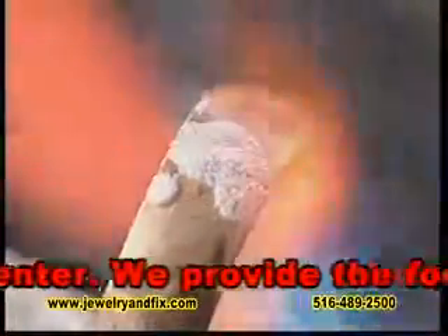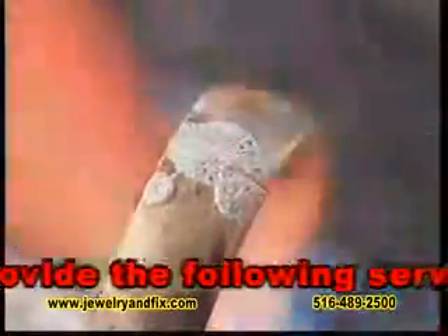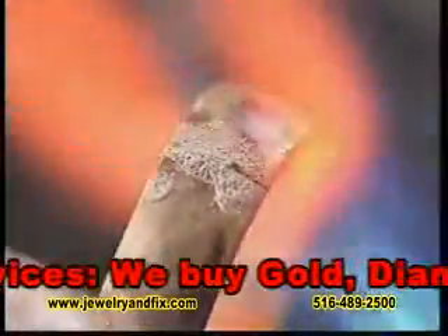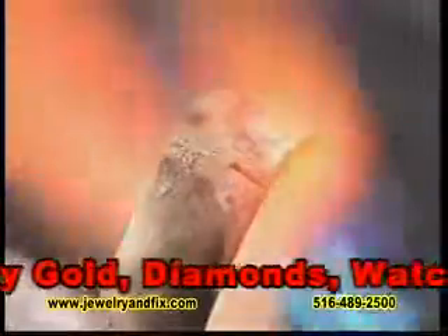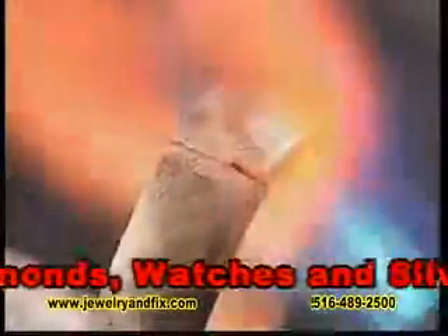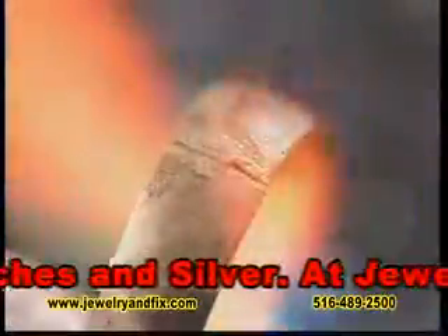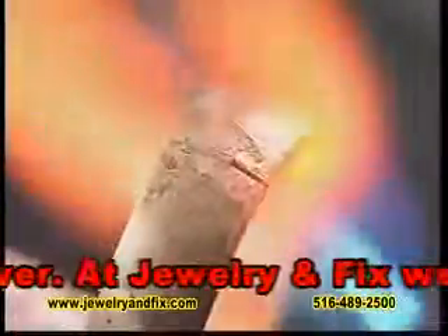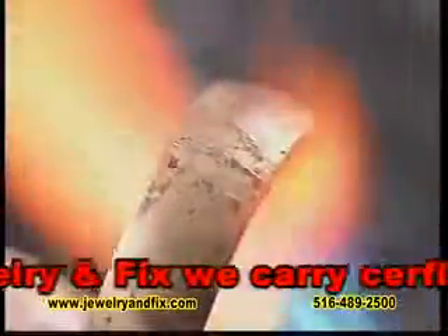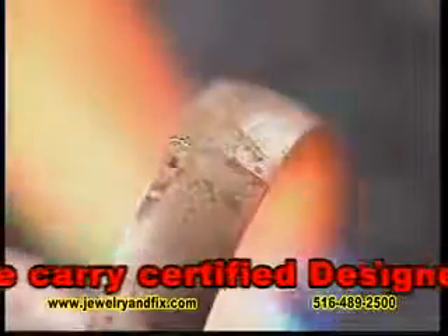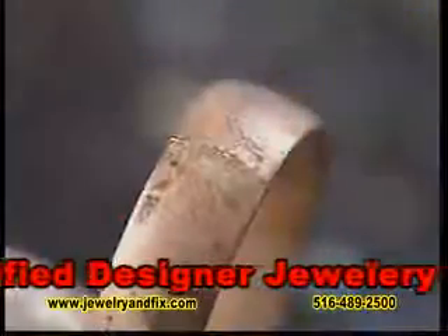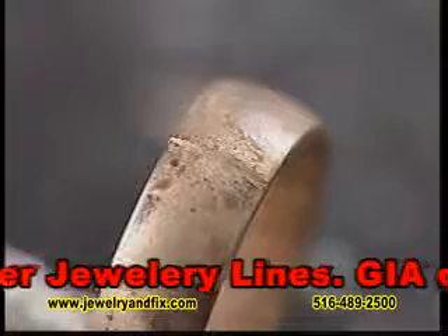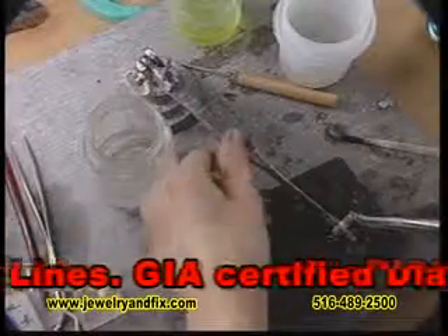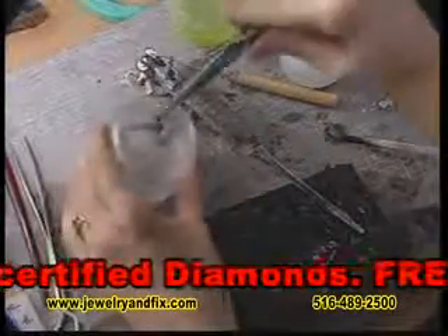You should use a slightly softened or reducing flame. You don't want an oxidizing flame which will create oxides on the metal. A flame with a pronounced hiss is an oxidizing flame. Move the flame across the joint so that you bring the metal on either side to the solder melting point at the same time. After the solder flows, quench, pickle, and rinse.